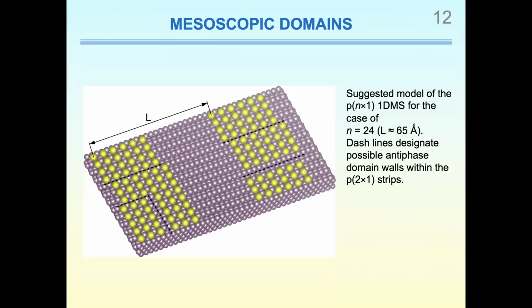Since the primitive 2x1 cerium-molybdenum 112 phase grows by the first order transition, there are islands occupied by the cerium film and areas of empty surface. Such a mosaic surface with different intrinsic surface tension is unstable to the formation of elastic stress domains. We suggested the formation of the one-dimensional mesoscopic superperiodicity observed by us in the primitive 2x1 overlayer is caused by the pointed elastic interaction. Evidently, the availability of sufficient areas free of adsorbate is an important condition for mesoscopic self-ordering.